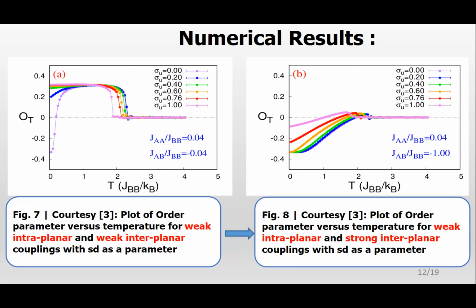So what happens is that when we increase the standard deviation of the external field, it destroys the magnetic order in the surface A layers of the ABA structure. When the surface A layers are almost randomized, only the mid B layer shows the temperature evolution of a particular ferromagnet that we see every day. So at about sigma equal to 0.76 or sigma equal to 1.0, only the B layer reacts like a conventional ferromagnet, and the surface A layers do not react with temperature. The temperature evolution gets destroyed by the application of the external field.